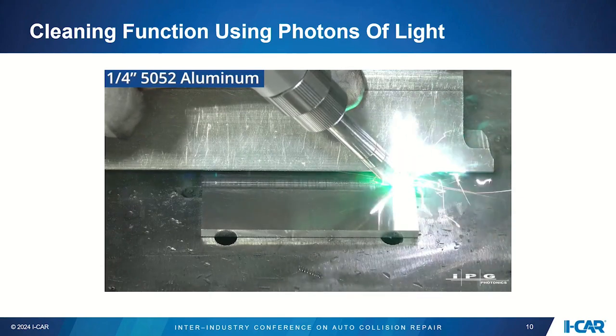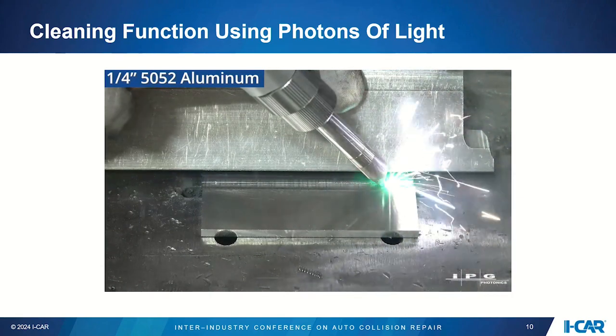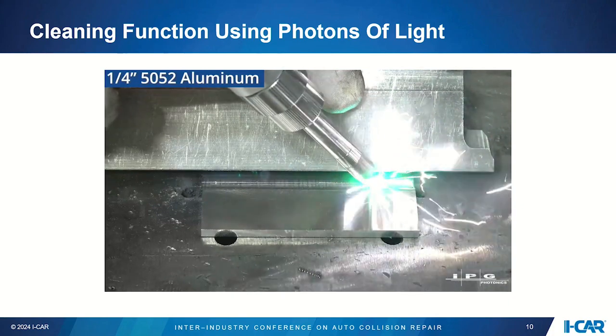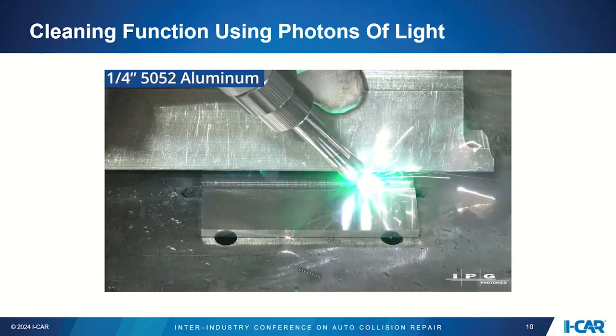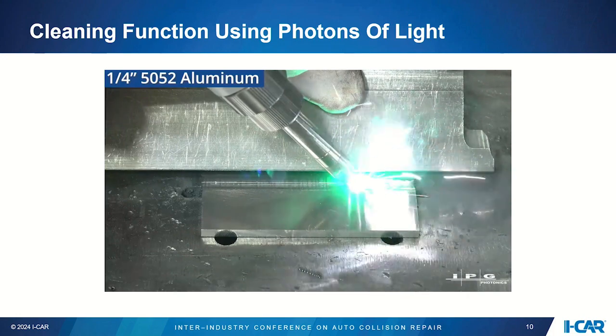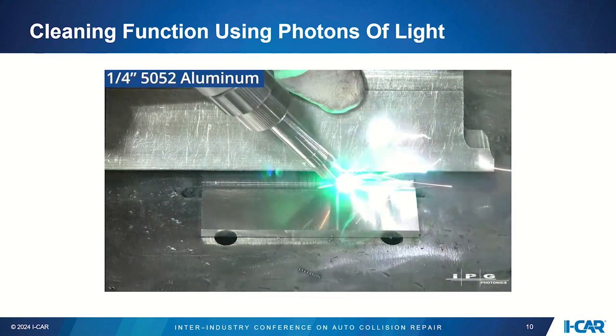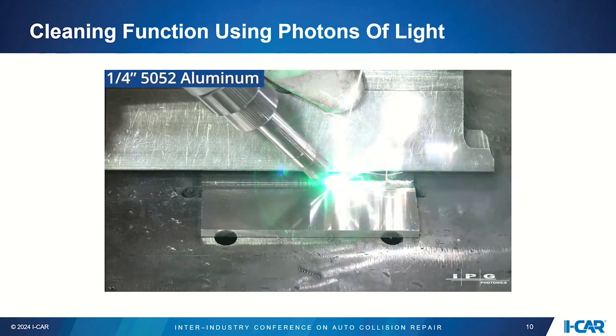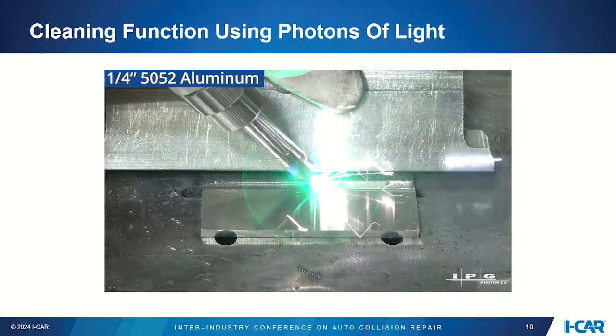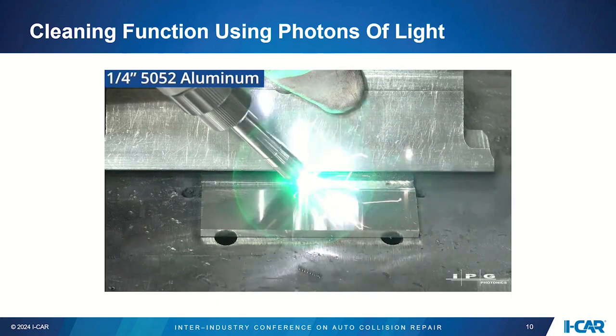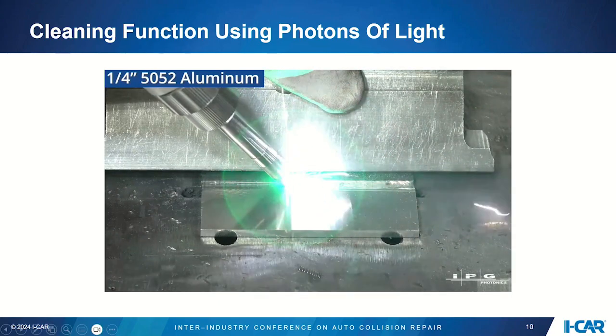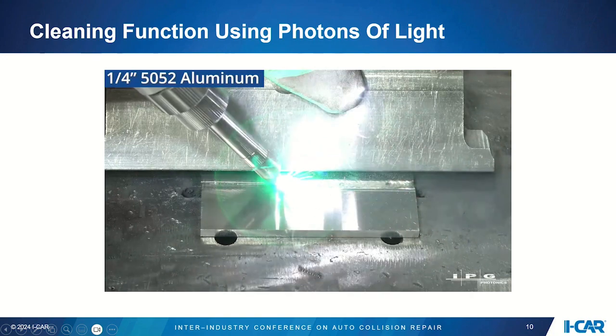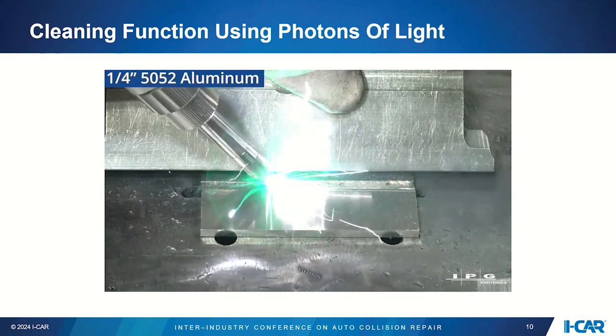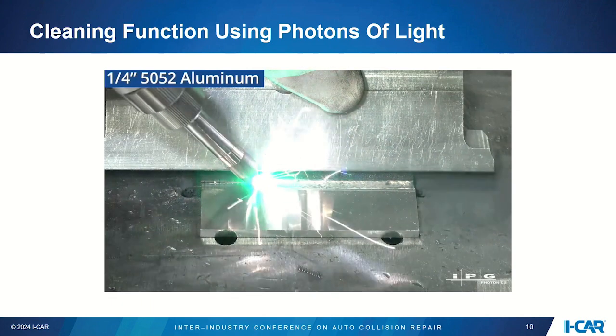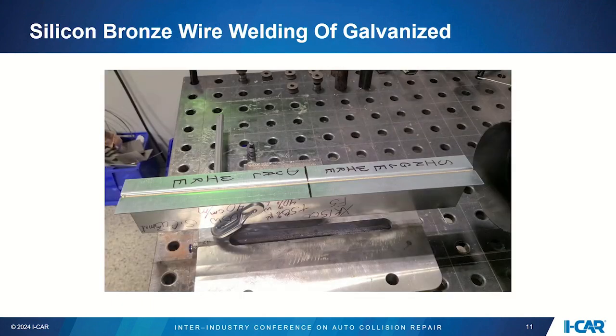And this is a fusion weld. That's 1/4-inch aluminum. That is not automobile specific. So basically, they're just butted together, and now he's coming along. And that's right. No filler wire. So this is the type of scenario where if there's any gap or void in there, that beam will get through and potentially affect something behind it. Yeah, typically, if you're not going to use wire, the amount of gap that's acceptable is about half of the material thickness. So if you have 20 thousandths material, that'll be a pretty good fit up. Hence you use the wire. Yep. So you can start this video also.